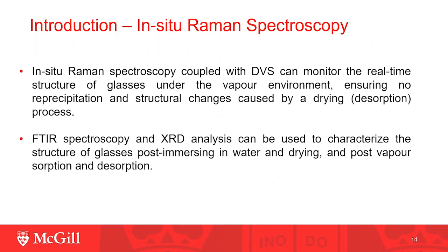Moreover, in-situ Raman coupled with DVS can monitor the real-time structure of glasses under a vapor environment, avoiding the structure change caused by a drying process, compared to FTIR and XRD analysis that can only be used to analyze the structure of the glasses post-exposure to aqueous environment and drying.